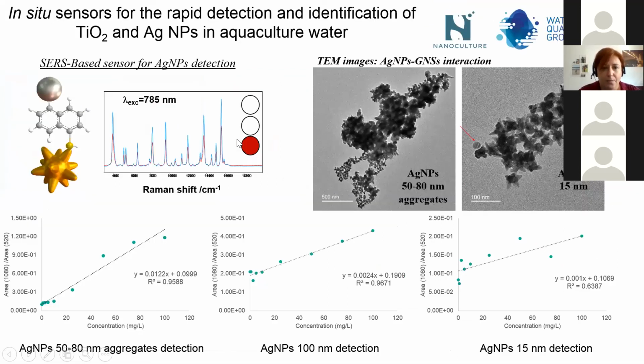Well, and then for silver nanoparticles, we are exploring another type of sensing method that is based on Raman spectroscopy. The signal from the molecules can be enhanced heavily by using plasmonic particles such as gold nanostars. What we are doing is to use a reporter molecule that has high affinity for silver nanoparticles, and it's attached to the gold nanostars. So when we have silver nanoparticles in the media, they will get attracted by this molecule, and this molecule has a signature in Raman.